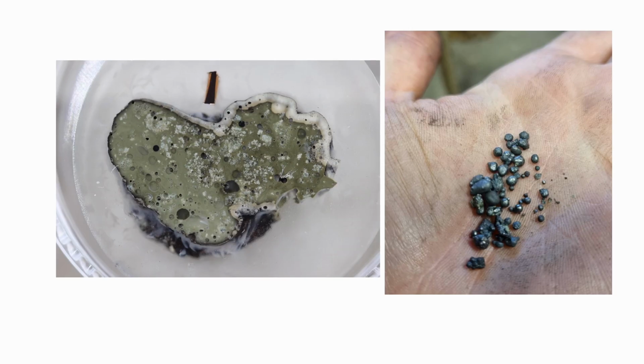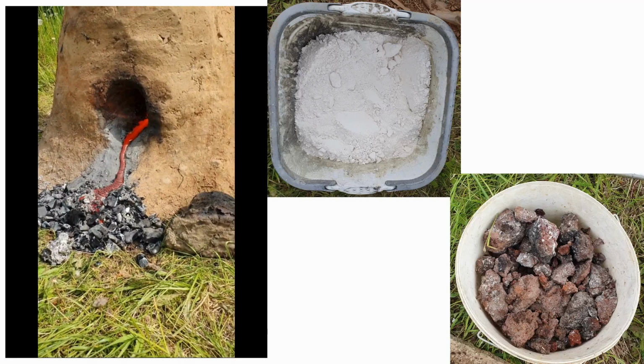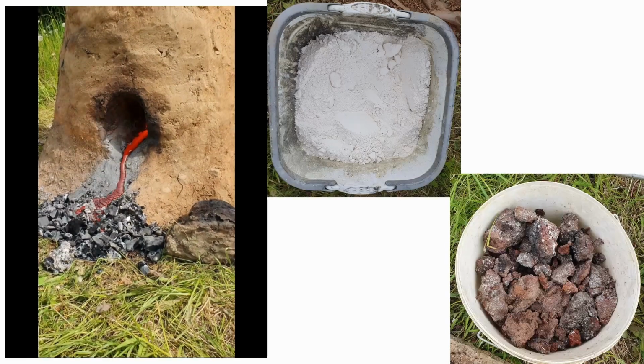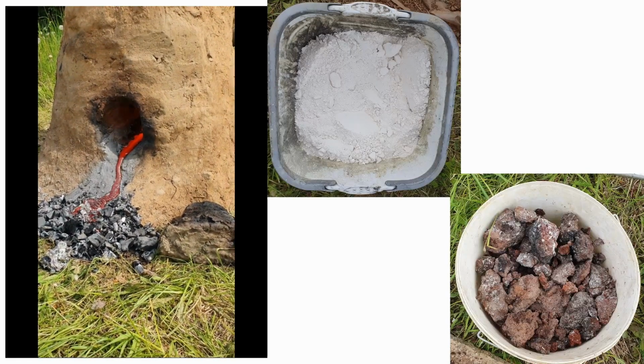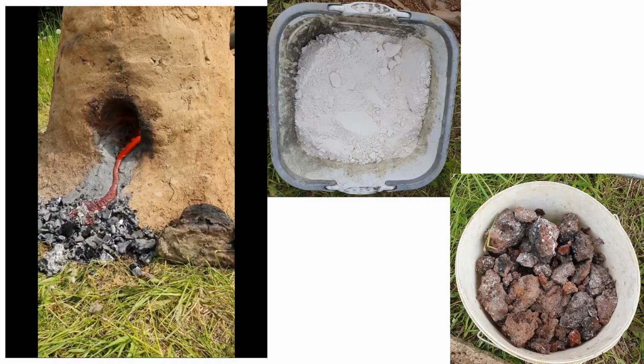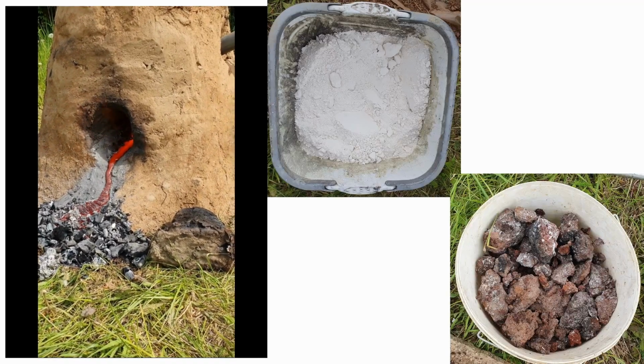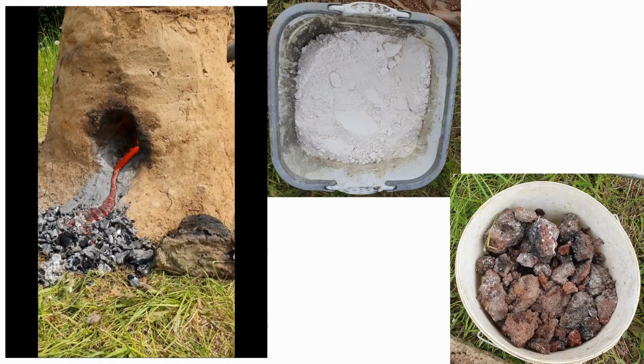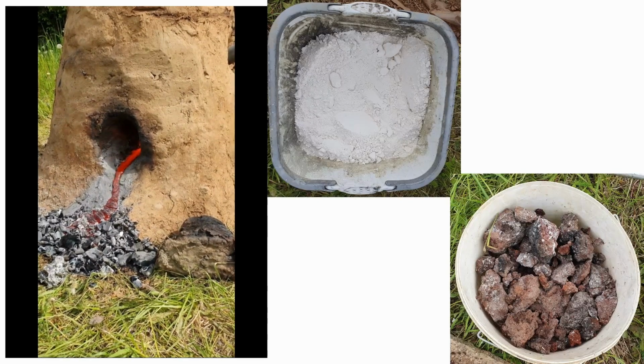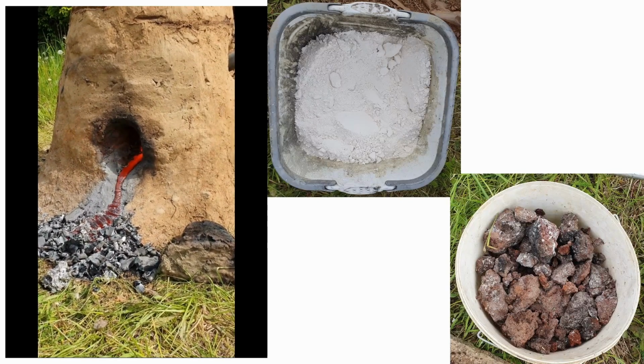Despite these adjustments, the slag viscosity remained unchanged, and it did not flow out of the furnace, while the amount of iron pearls even decreased. Then we reduced the blowing intensity and introduced slag lime powder as a flux to lower the melting temperature and viscosity of the slag. This is particularly important for phosphorus-rich ores, since calcium helps prevent phosphorus from transferring to iron.